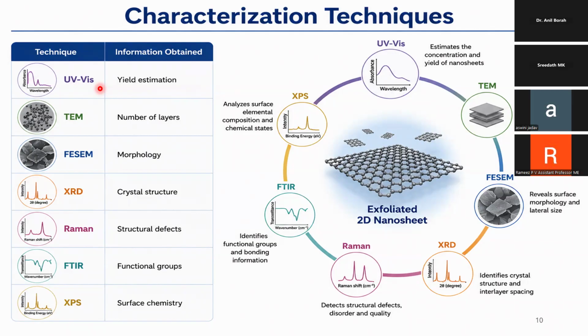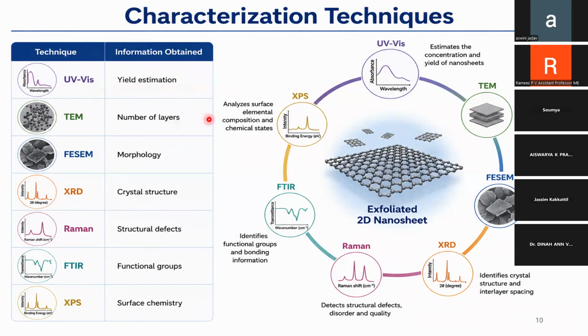Okay, so likewise, TEM is used for finding out the number of layers, because when you visualize the bulk material with the TEM, as this is transmission electron microscopy, it will appear as an opaque structure. But when you keep single layered hBNNS or single layered graphene, you can see more transparent kind of images. So by that, you can predict that the number of layers has been reduced, and you can actually count the layers as well.